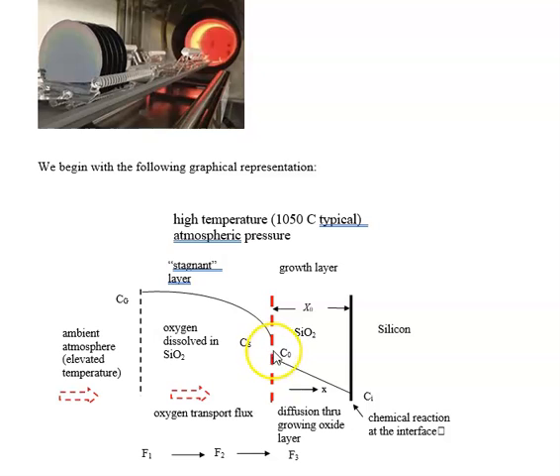However, the oxide does not grow here. Oxygen is pushed in to the growth layer, diffuses through the growth layer until it gets to the silicon layer. There's no way I can grow glass on SiO2. I need to grow glass on silicon. So the reaction takes place here, and we'll see it's the simple reaction. Silicon plus oxygen equals glass. It's a first order reaction because it is controlled only by the concentration of oxygen at the surface. We're assuming we have an inexhaustible supply of silicon.